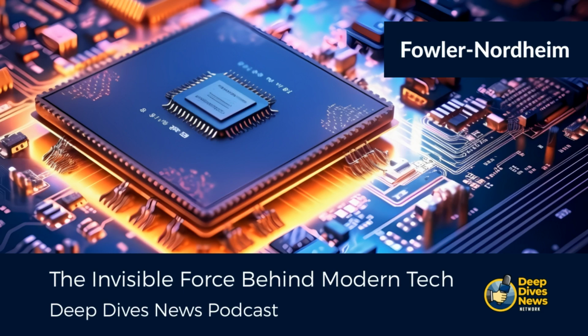Okay. Now, the sources also got into some really cutting-edge stuff, using silicon nanowires in memory. That sounds incredibly tiny. It really is. Researchers are pushing the boundaries with silicon nanowire, or SiNW-based memory, often in a structure called SONOS. SONOS, like the speaker? No, different SONOS. It stands for silicon oxide, nitride, oxide, silicon, all about the layers. Okay, layers. Yeah, this layered structure is crucial for controlling the electric fields needed for that FN tunneling we talked about. Right. And what's really fascinating is how the incredibly small size of these silicon nanowires, we're talking diameters often around, say, 20 nanometers, can significantly boost performance.